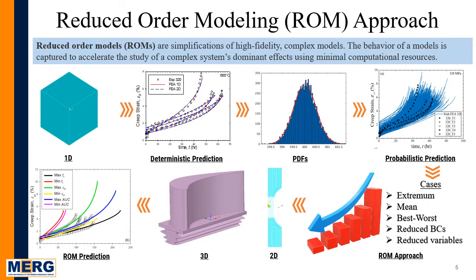In this work, we adopted this reduced order modeling approach to rapidly qualify the creep properties of a complex geometry. Reduced order models are simplifications of a high-fidelity complex model. Herein we take a very simple 1D geometry and apply all the creep properties along with the testing conditions to do the deterministic simulation, to compare and validate the creep damage model against prior creep data. Now we assess the different sources of uncertainty that are going to affect the creep. We establish the probability distribution functions for each of the sources of uncertainty, and those PDFs are fed into the finite element settings to do the numerous probabilistic predictions.